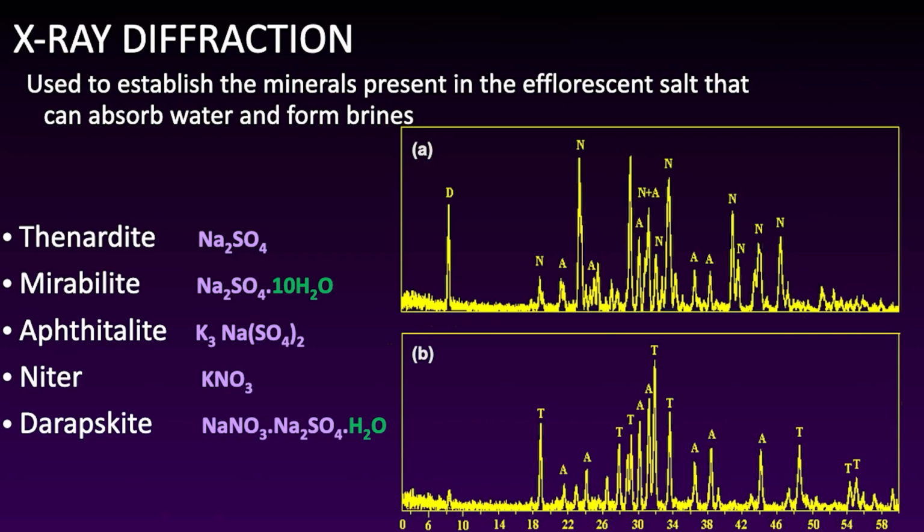And this occurs usually at a very specific relative humidity. So every time you cross that relative humidity, you get a crystallization event or an event where the crystals dissolve and form a brine. And in the case of sea salt, sodium chloride, this occurs very close to 75% relative humidity. So you can see in this particular set of data how, a few times each year, there's a transition to a drier, lower relative humidity, and crystals form, and so this leads to salt crystals forming and thus salt weathering.